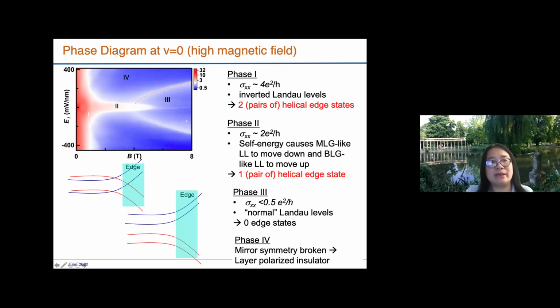Okay, and phase 4 happens... So phases 1, 2, and 3 happen around zero electric field. That happens as long as the mirror reflection symmetry is not broken, so that even or odd parity is a good quantum number. At a larger electric field, we are explicitly breaking the mirror reflection symmetry. Then the bands start to hybridize, and now what we're creating is basically pushing the charges to reside on either the top or the bottom layer, so it's a layer-polarized insulator.